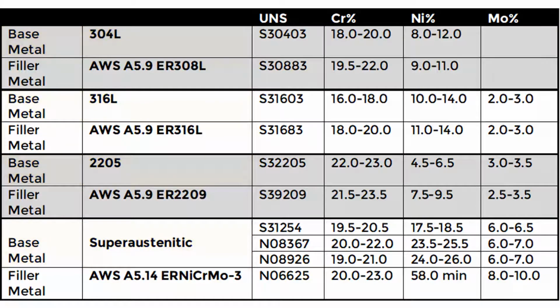Here we can see that the filler metal for 304L and 316L is only slightly overalloyed in chromium. These stainless steels are routinely autogenously welded and possess satisfactory corrosion resistance in service. The filler metal for 2205 is significantly overalloyed with nickel. This higher nickel content ensures that the solidified weld metal possesses the optimal duplex microstructure that is not overly ferritic, which can compromise the corrosion resistance and toughness of the weld metal.